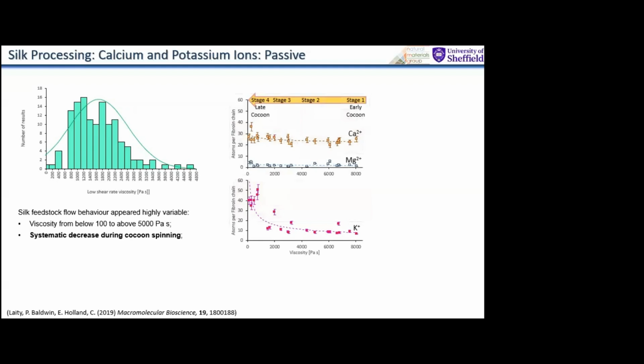So we started to look at the metal ions present in the unspun silk as we tested it. And what we saw was a very, very consistent pattern, from early cocoon, early spinning, to late cocoon, nearly finished. We find that calcium's basically exactly the same, magnesium's basically exactly the same, but potassium increases as the silkworm starts spinning more and more and more. We get this increase in potassium ions that seem to be linked to a reduction in the viscosity.